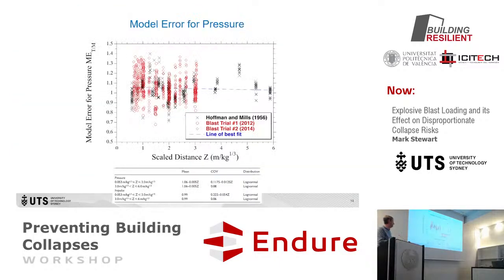And then we start thinking about, if we compare the test result to the model that's used to predict the blast pressure, we can work out what the error is between the model and the test result. Obviously, if it's 1, that means it's perfect, and the average result is about 1, which is pretty good. But there's a pretty large scale, plus or minus. Some pressure values are 40% higher, some are 30% lower. So we want to consider that in terms of, in this case, log normal distributions.